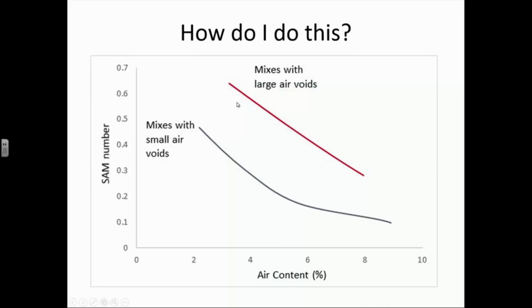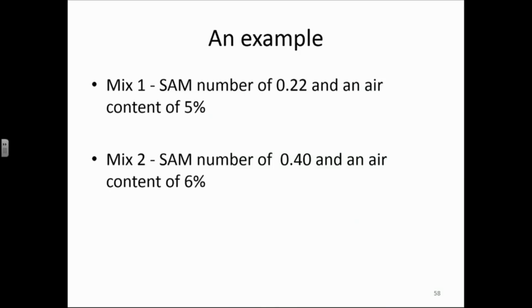Okay? But based on about 600 different concrete mixtures, those with large air voids plot near this top line, and mixtures with small air voids plot near this bottom line, or possibly below. And this means that you could plot for your concrete mixture a single point and you would know immediately what was going on. So for example, I have two mixtures. This is where everything was going great for mixture one. This is real field data, by the way. Everything was going great at mixture number one. They were getting a SAM number of 0.22, an air content of 5%, and all of a sudden they got a SAM number of 0.40 and an air content of 6%. And they said, what? What's going on?